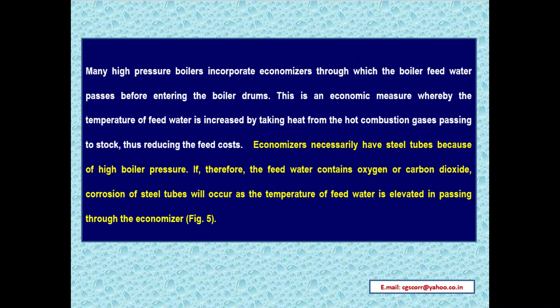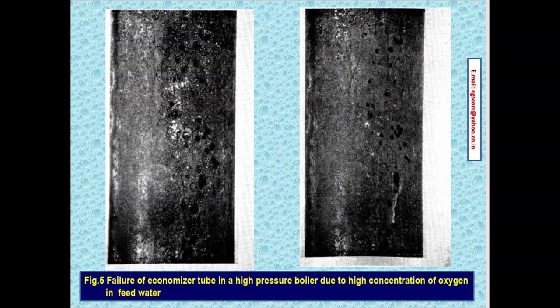Economizers necessarily have steel tubes because of high boiler pressure. If, therefore, the feed water contains oxygen or carbon dioxide, corrosion of steel tubes will occur as the temperature of feed water is elevated in passing through the economizer. Figure 5 illustrates the failure of an economizer tube in a high pressure boiler due to high concentration of oxygen in feed water.